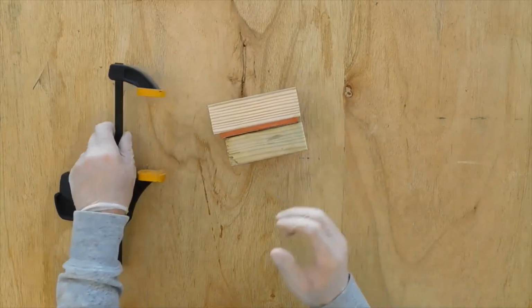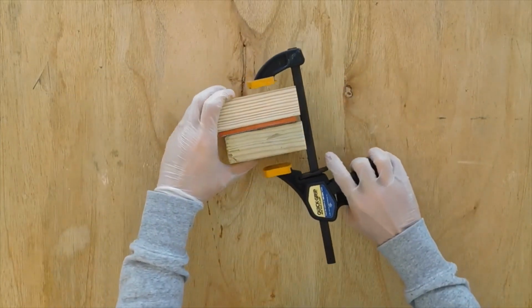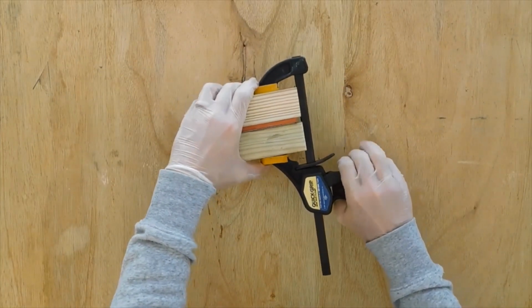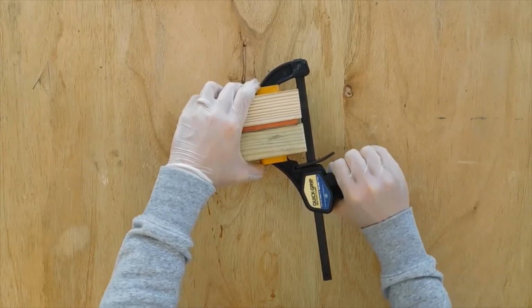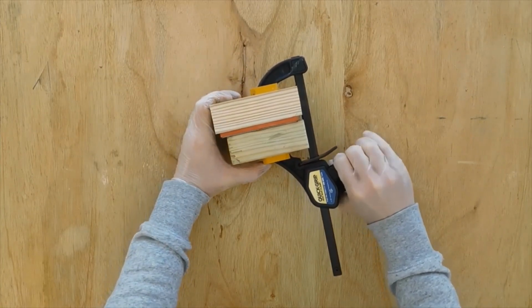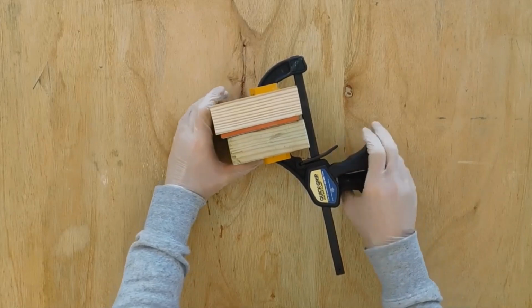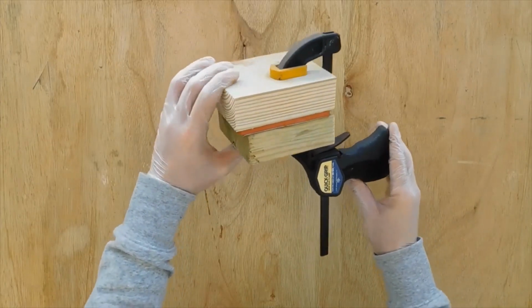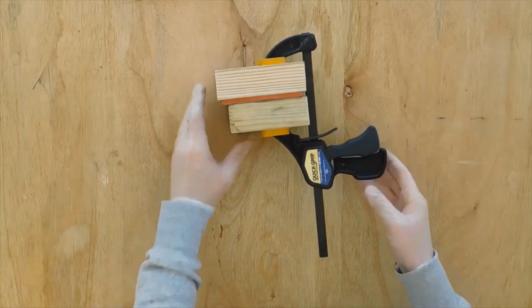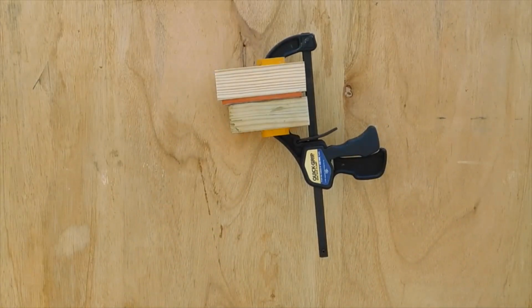Cure is a function of time and temperature. Room temperature cure around 75 F will need 3 to 7 days for the catalyzed adhesive to develop maximum strength. The cure time can be shortened by elevating temperature to a maximum of 329 F. A typical shortened cure cycle is 24 hours at 77 F, followed by 24 hours at 212 F.